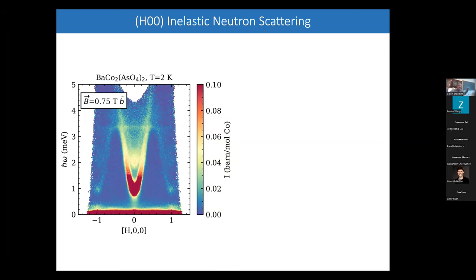So I've now driven it into a kind of polarized paramagnet. So it's in a highly magnetized state, almost fully magnetized. And we get this kind of parabolic dispersion relation, which is very much what you'd expect for a 2D ferromagnet. But I still have very strong intensity here at the 2-magnon location, and also additional continuum scattering within the cone itself.